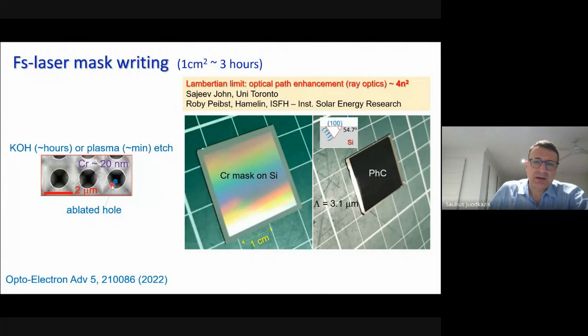Can we make patterns which are periodic on silicon? So we coated chromium and we ablated with laser, and then we used plasma etching or wet etching to fabricate pyramids, which are periodic structures on the surface. After the chromium mask is removed, we have a black surface, which is good. It shows that light is not reflected but absorbed.